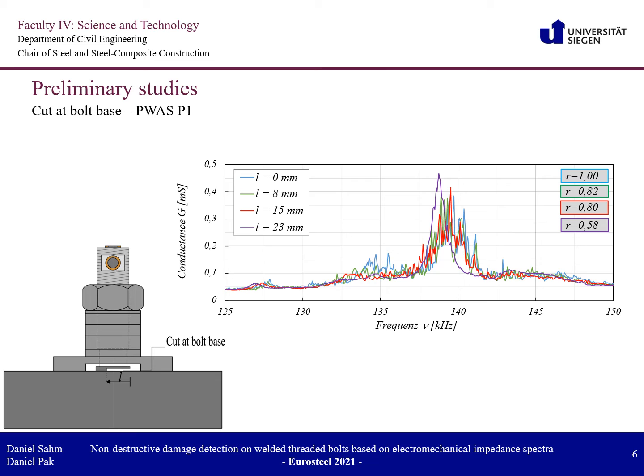Only in the 23 mm series of measurements, a larger local peak and the visible shift to the lower frequency range is discernible. In summary, it can be deduced from the preliminary test that an increasing change in the stiffness of the structure, in this case in the form of the cut, also results in a reduction of correlation, and it's therefore detectable in principle.